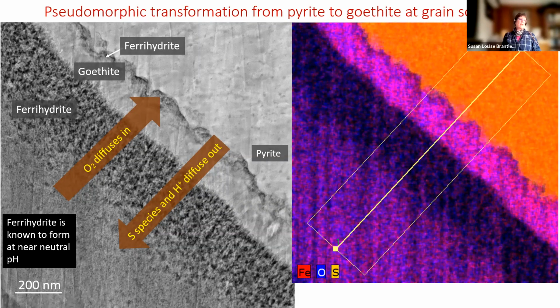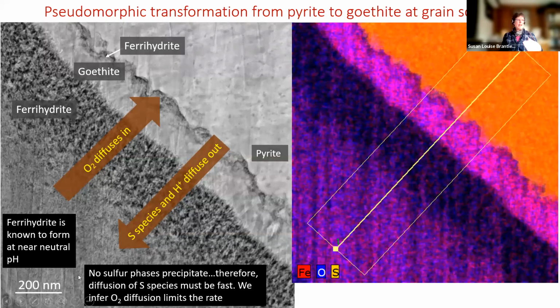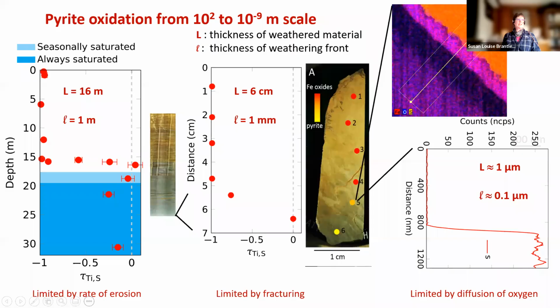Ferrihydrite is known to form at near neutral pH, and so we think that the H+ is neutralized by the shale, which is on the outside here, and we never see any sulfur phases precipitating. So we think that the diffusion of sulfur species must be fast, because we never see it hanging around. We either see the iron sulfide pyrite or we see iron oxide, and the sulfur is gone. So we've inferred again from this that oxygen diffusion limits the rate.